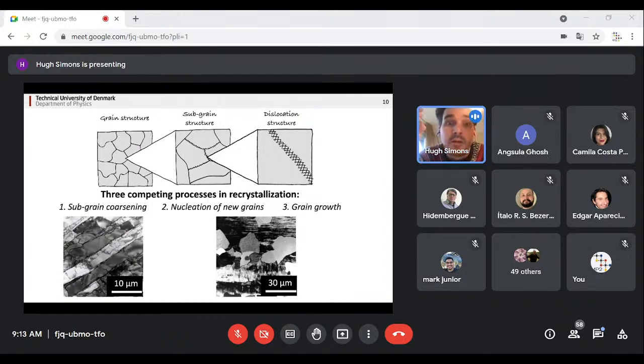So there are effectively three methods for recrystallization in aluminium. The first is subgrain coarsening, where these subgrains get larger and eat each other, for lack of a better expression. There's the nucleation of new grains, where new grains will form and grow at the expense of others. And then there's classical grain growth as well. One of the real questions is to what extent these three processes take place under different conditions in recrystallization. It's tremendously fundamental to how we use and process something like aluminium, but there's no clear consensus on it today.